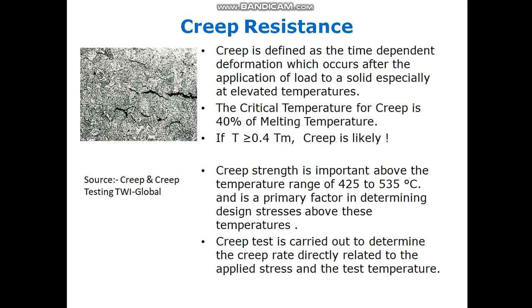Creep strength is important in the temperature range of 425 to 535 degrees Celsius and is a primary factor in determining the design stresses above this temperature. In the picture you can see a material that has cracked due to creep. A creep test is carried out to determine the creep rate, which is directly related to the applied stress and the test temperature.